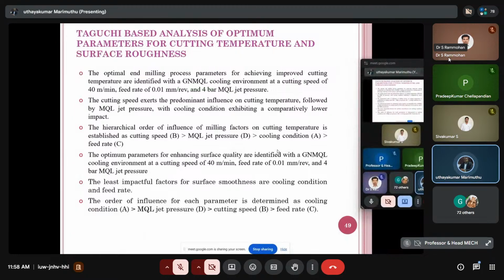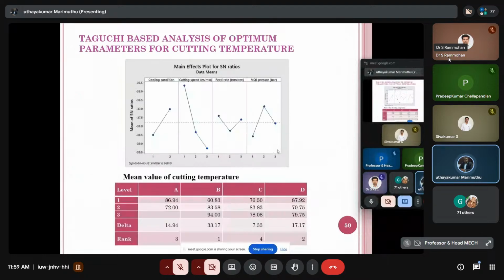The optimum parameters for enhancing surface quality are identified with the GNMQL cooling environment at a cutting speed of 40 meters per minute, feed rate 0.01 mm per revolution, and 4 bar MQL jet pressure. The least impactful factors for surface smoothness are cooling conditions and feed rate. The order of influence for each parameter is determined as cooling conditions A, MQL jet pressure D, and cutting speed B, then feed rate C.